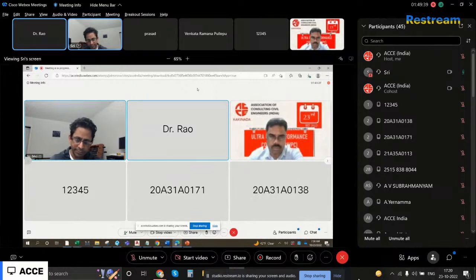That's why we are getting much more density for the latest concrete mixes, where we are using blended cements that give secondary hydration. That gives much more pore refinement than the initial primary hydration, from 25% white space to almost 1% white space. We are filling almost the entire white space with the secondary hydration products. That is the main reason. Besides that, if you change the specific gravities of the aggregate materials, definitely there is a change in the density of the final product, like we have the special concrete.